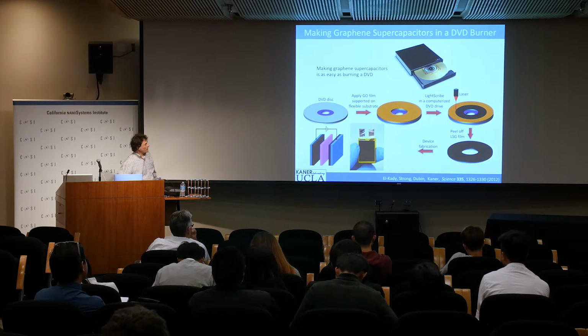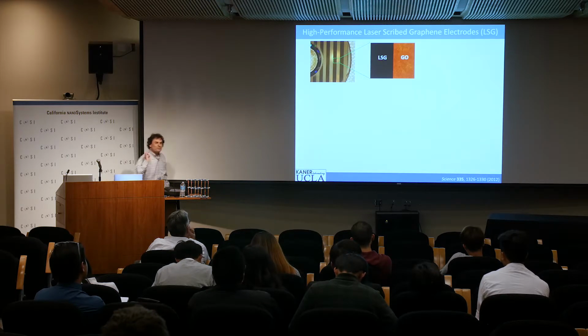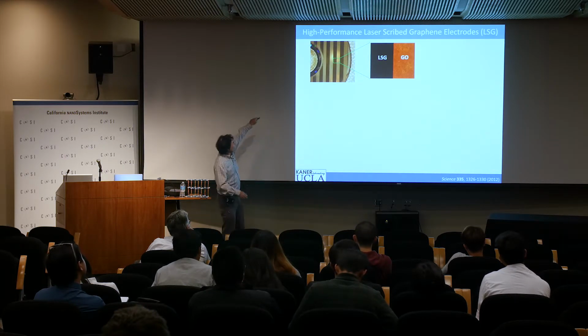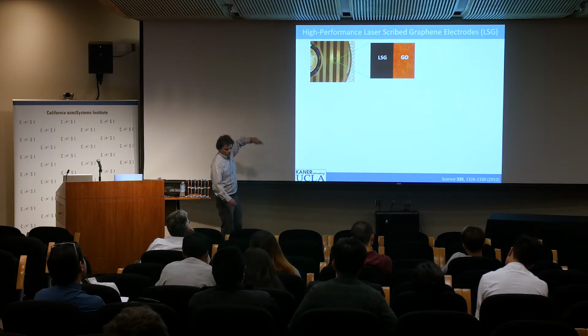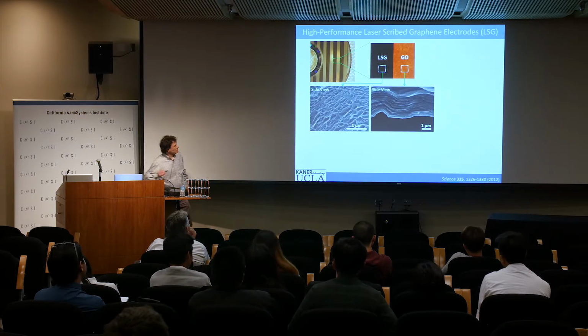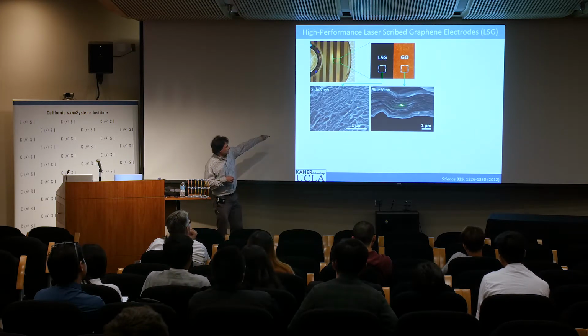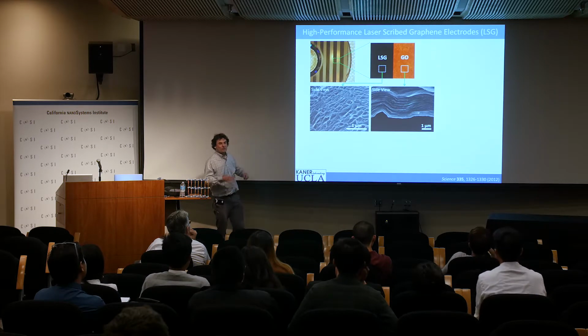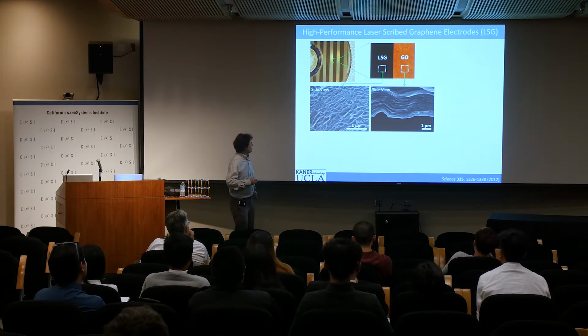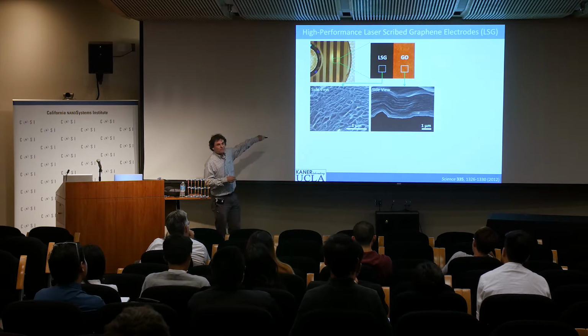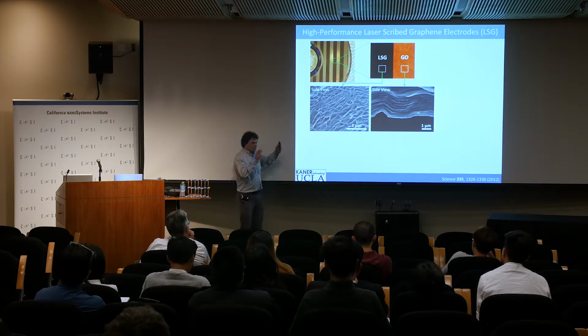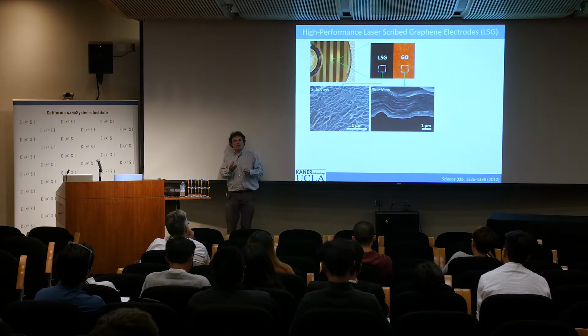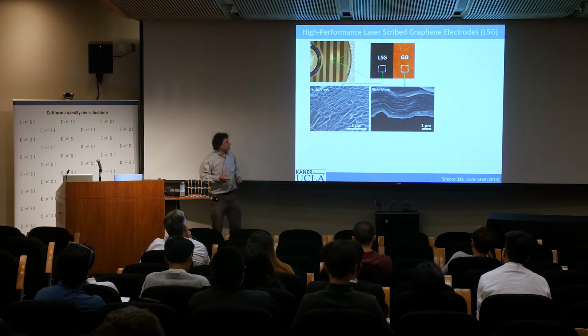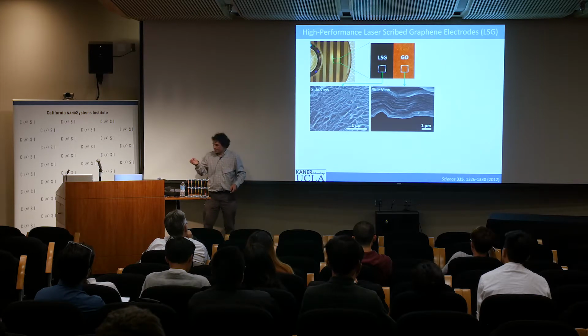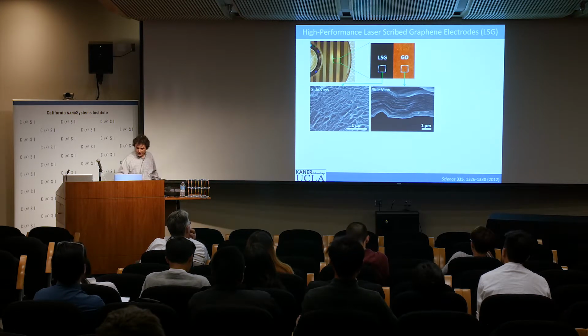And this is going to look like a battery. It works a little bit differently. But here's the most important slide I'll show you. Here we told the laser just to draw stripes. So this is graphite oxide in one stripe, and there's the LightScribe graphene. And what's interesting is what we made. So the graphite oxide is this nice layered structure. After we hit it with the laser, it absorbs the light, it gets hot, it blows off carbon dioxide, and what we create is a fractal. And so these are sheets of graphene, but it's really disordered. It's three-dimensional, and it's non-collapsible. This is exactly what you want for storing energy because you have high conductivity, high surface area, and it's inexpensive.